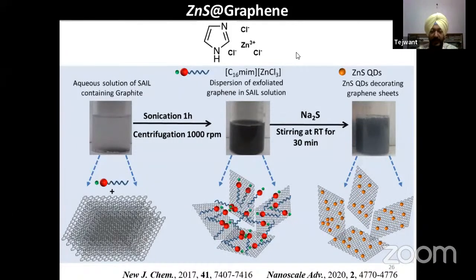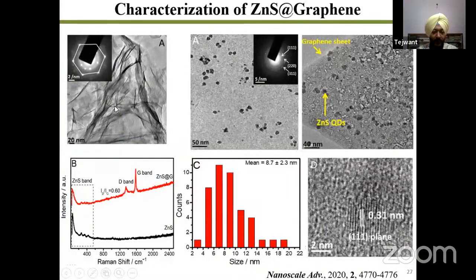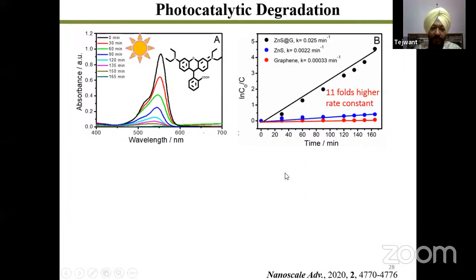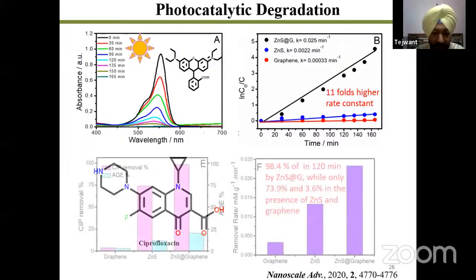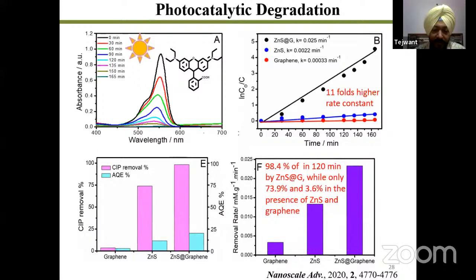Similar studies like I have shown you earlier have been performed. So these are the TEM images for graphene with zinc sulfide nanoparticles and the zinc sulfide quantum dots, and the presence of zinc sulfide quantum dots at the surface of graphene sheet has been shown by transmission electron microscopy. Both the nanoparticles as well as the graphene surface have been characterized by Raman spectroscopy as well as transmission electron microscopy. So similar photocatalytic material has been used for the photodegradation of rhodamine B. And again, ciprofloxacin has been tried, and this work has been published in Nanoscale Advances in the year 2020.